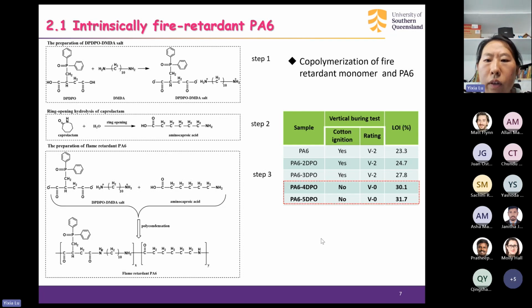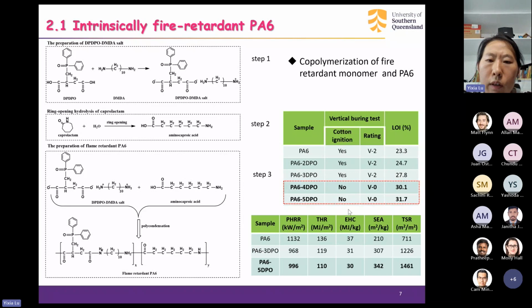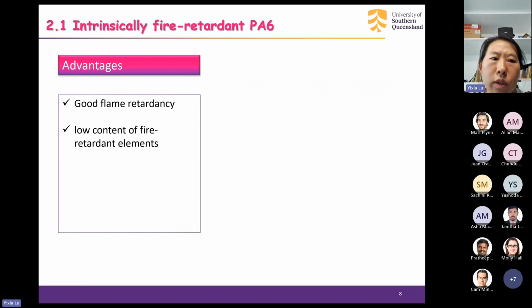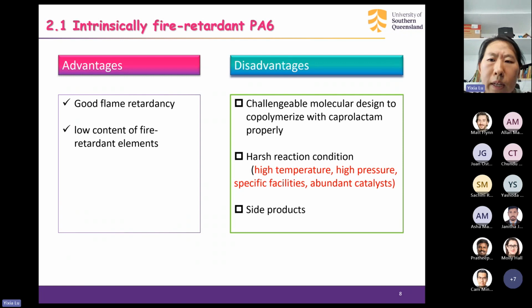This kind of method requires a lower content of elements, so it has advantages like good flame retardancy and lower content of the fire retardant elements, but it also has some disadvantages like challenging molecular design to copolymerize with caprolactam properly. Also, during the synthesis, harsh reaction conditions are always needed, like high temperature, high pressure, specific facilities, abundant catalysts. Also, we usually find some side products are generated in the reaction.